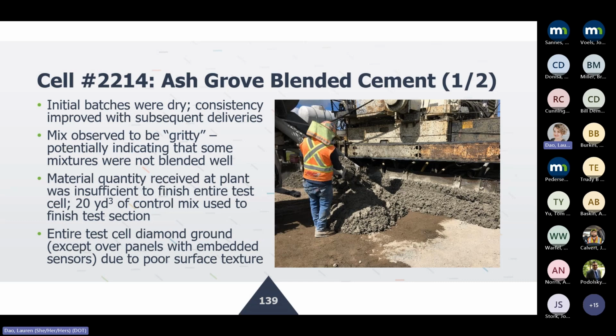Probably an artifact of the super sack issue, and the material received from the manufacturer was not enough to finish the 240-foot test cell. So we had to backfill it with the control section, and the entire test cell was diamond ground for this particular cell, except over the panels with the sensors.